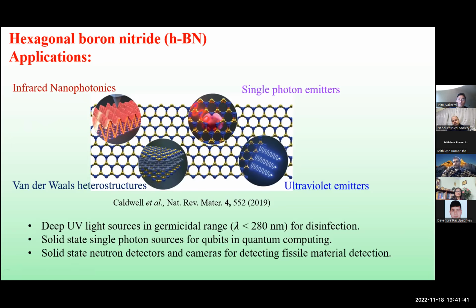Wide bandgap materials have a forbidden gap so wide that when there are some impurities or defects, or even dislocations, their energy levels can be within the band gap. Those impurity or defect energy levels could sometimes be donors, sometimes acceptors, and sometimes just electron traps. Some of those defects could also be very highly localized states, and transitions in those states can give single photon emission. So I am going to discuss what we observed, very close to that single photon emission.